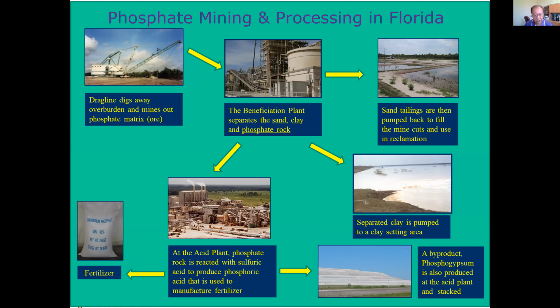So this phosphate rock product is shipped to the acid plant where sulfuric acid is added to react with phosphate rock to produce a slurry of phosphoric acid and phosphogypsum. This slurry is filtered using a filter pan or other type of filters to separate the phosphogypsum from phosphoric acid. The phosphogypsum is pumped to a stack, gypsum stack, and the phosphoric acid is further evaporated to increase the P2O5 content. The filter acid generally contains about 30% P2O5. And by a two-stage evaporation process, the acid is concentrated to roughly 54% P2O5.